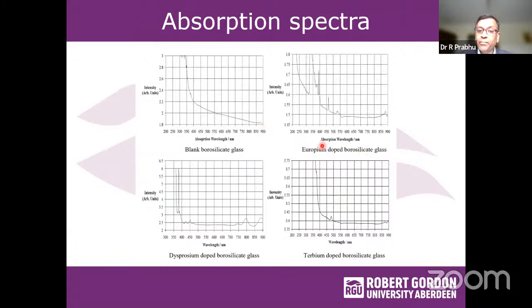Again, if we dope europium in this glass matrix, you can see the characteristic absorption peaks of europium. These are sharp absorption peaks around 470, 385 in the near UV, and around 532 for europium. Similarly, you have for dysprosium a UV peak as well as some visible peaks. For terbium, you have a visible peak around 474.88 and a UV peak. So in general, we can use these rare earth elements for generating strong absorption bands around the near UV as well as in the visible.